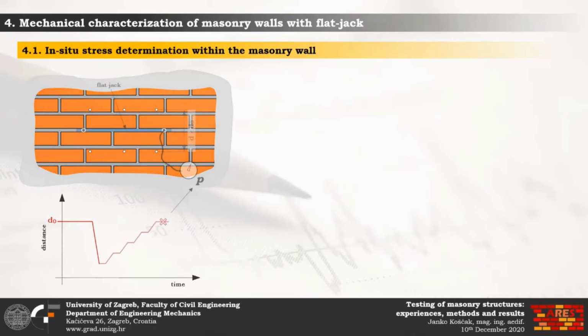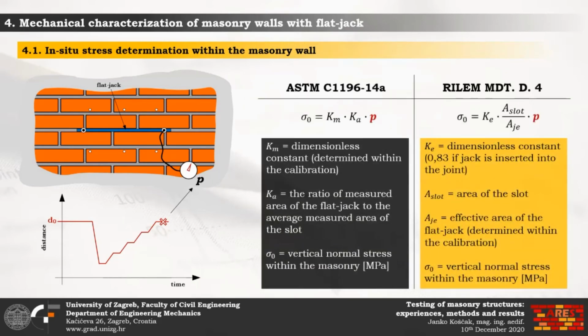Now the flat jack should be inserted into the slot to compensate for the released pressure. The flat jack pressure is applied in increments until the distance between reference points attains the same value it had prior to the slot cutting. At this point, the pressure of the flat jack is taken, and the vertical normal stress can be calculated according to one of those expressions. So one can choose either a standard or RILEM procedure depending on the calibration procedure.